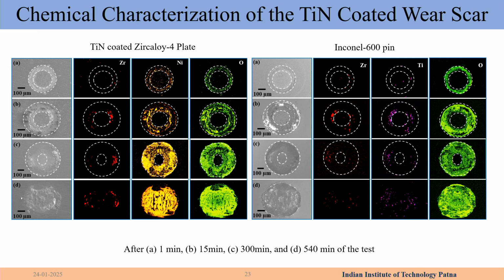And then you can see these pictures of the TiN coated Zircaloy plate with Inconel pin. These are the pictures after 1 minute, 15 minutes, 300 minutes, 540 minutes after the test. How it changes, all of them are going into sliding at the end, you can see, but the titanium nitride coat actually increases the time. If you see there, at 120, 130 minutes we had complete sliding. In this we are going to 540 minutes.